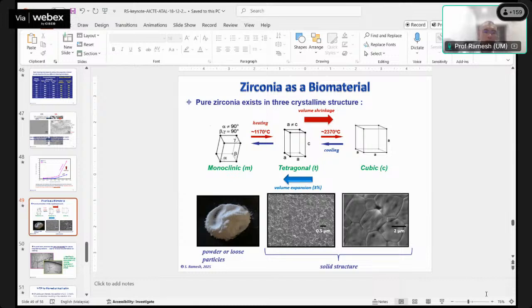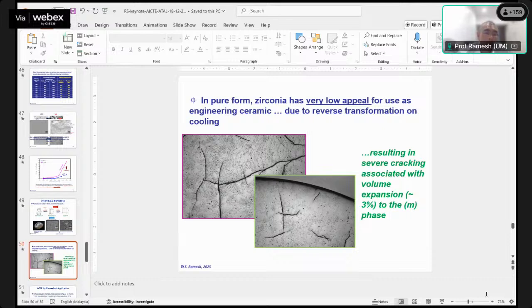In order to ensure that the reverse transformation does not take place, pure zirconia is normally not used in its pure form. It is normally doped with a stabilizer like yttria or cerium oxide or magnesium oxide and so on. In pure form it is not used because on cooling there is expansion, from tetragonal converting back to monoclinic. As a result, there's severe cracking.